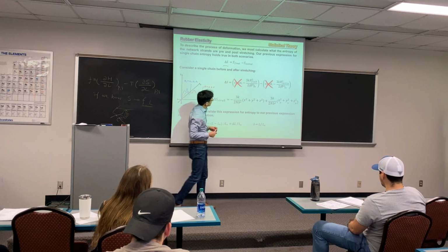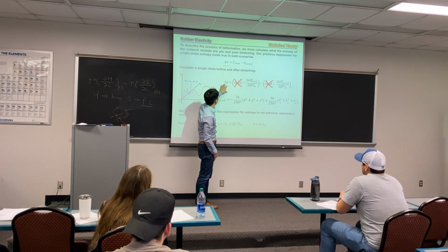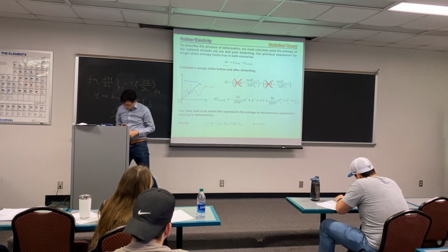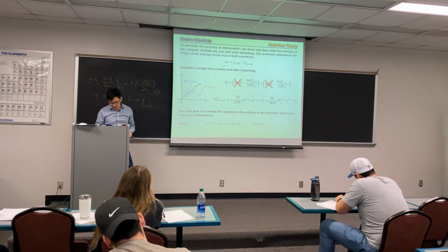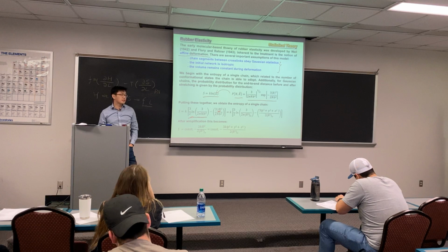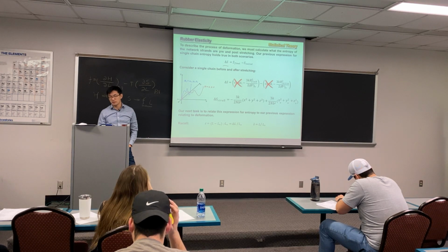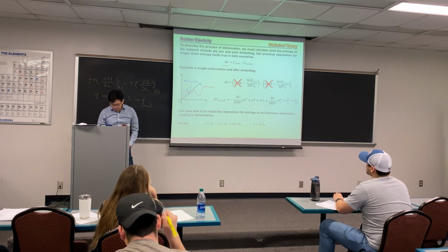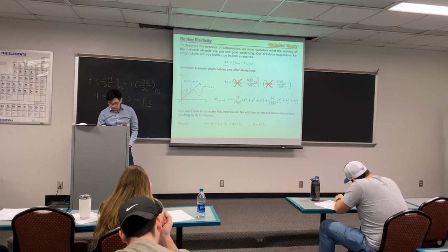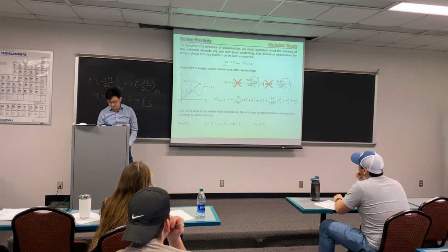Some characters are not showing up properly, so this should be the final. So what we want to calculate is delta S as the final minus the initial. The constant will cancel because they are exactly the same term as shown here. So when you consider the final minus initial, this constant term will cancel, so we don't need to worry about that. The only thing we need to worry about is what I circled here, R squared final and R squared initial, and the rest is the same, right?